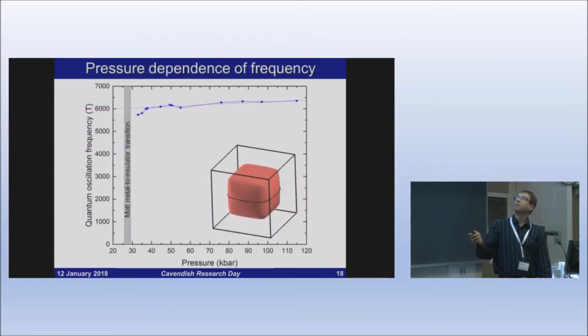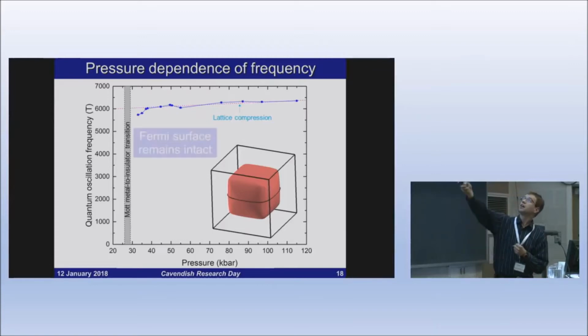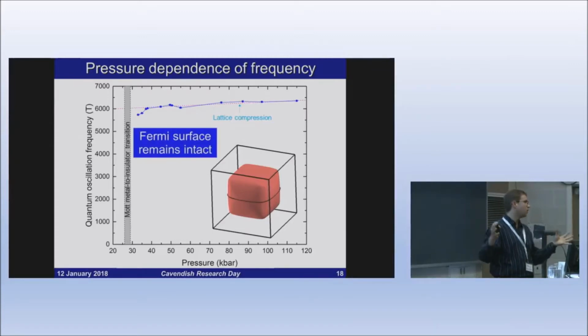So if we look at the quantum oscillation frequency as a function of pressure, as we're sitting in the metallic state and turning down in pressure, moving towards the metal-to-insulator transition, we see that it's not varying dramatically. So the area of this orbit, the area or volume of the Fermi surface, is not dropping drastically as we approach. In fact, most of this change is just due to simple change of the lattice constants as we squeeze the sample. And so we see that the Fermi surface remains intact. This means the carriers remain there. They're not disappearing as we approach the metal-to-insulator transition.